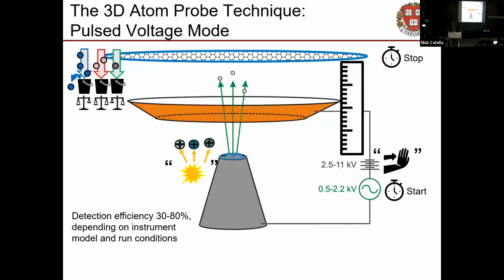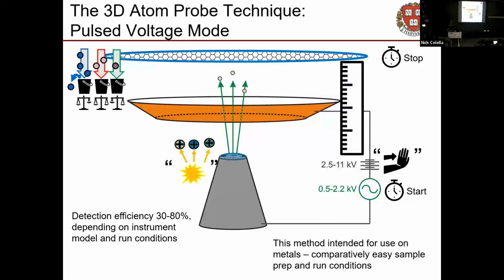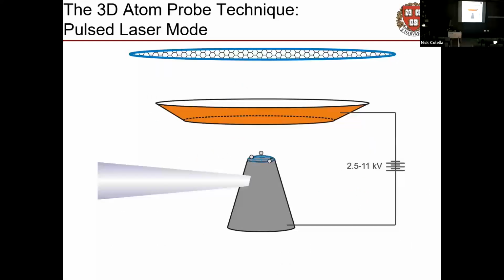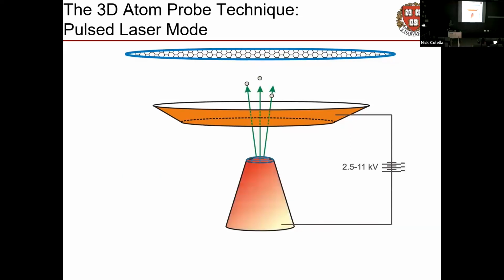And this works great as long as your sample's a metal, a pure metal, like a piece of aluminum or something. But if you actually want to work on an interesting material, this doesn't work so well because that voltage pulser is not very effective for things that are not a piece of aluminum. So for anybody's real sample, we're going to use a laser because we love lasers. They're great. We're going to use a pulsed laser, which means a laser that shoots extremely short time duration pulses of light, a few picoseconds. We shine that on, we start our stopwatch. The tip gets hot, very briefly hot. Not a lot of energy we're dumping into this, a few picojoules, that's all it takes.